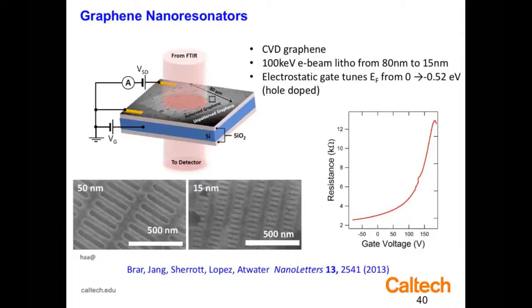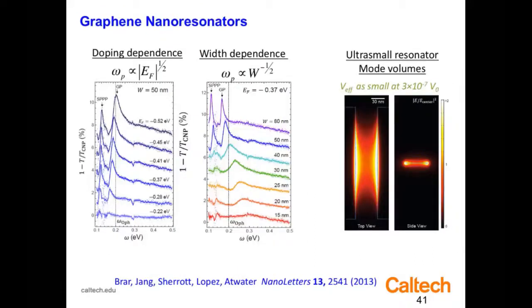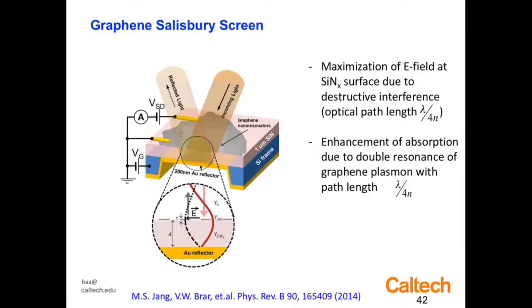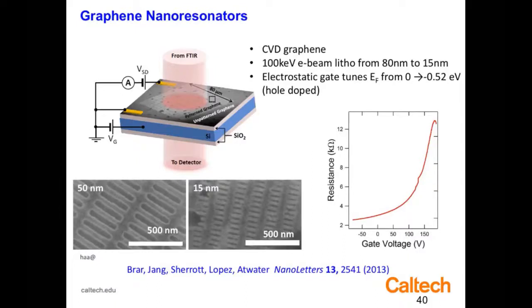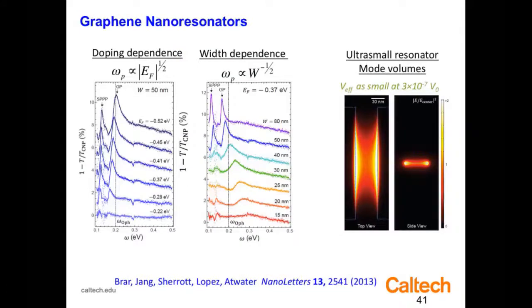We can tune the electrical conductivity from being highly resistive near the Dirac point to being highly conducting, and change the permittivity from positive to negative. The electromagnetic modes exhibit extreme confinement. The modes are confined within a couple of nanometers of the graphene sheet itself. The fine print here shows that the mode is 30 nanometers wide. That's in one of these, here's a 15 nanometer ribbon, here's about a 40 nanometer ribbon here. So if I were looking at the mode, I would see this kind of confinement. So basically what it says is that the mode is sampling and interacting with this extremely small environment. So this is a powerful thing, and in fact, other people in this field are using these as single molecule sensors, because you can drop a single molecule into this regime, and all of the light that's interacting with the graphene interacts with single molecules.